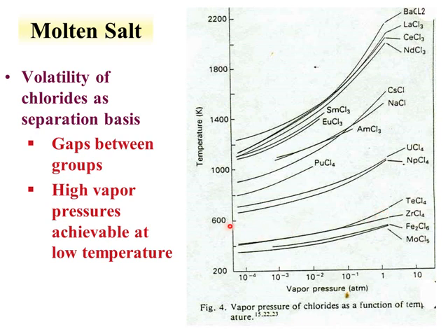At these temperatures, you can get 1 atmosphere vapor pressure for these elements at 600 K or less. So these can be relatively easily separated. And then for the actinides, you tend to get uranium and neptunium together, plutonium with some of the tetravalent and some of the trivalents, and then some of the lanthanides separated off into a different phase. So again, higher vapor pressures can be achieved at lower temperatures with some of the chloride systems, and this can be used for exploiting separations.